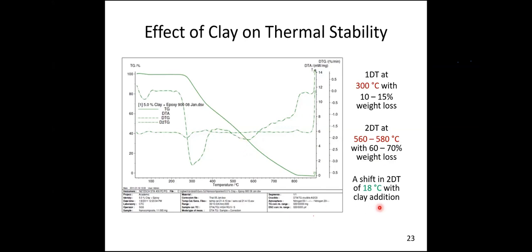So what is the outcome? With the addition of clay in epoxy, we could see a shift in the decomposition temperature. Because clay is a ceramic material, it has silica and alumina, of course. Because of this ceramic composition, we got better thermal stability. This is what we have found from the thermal properties.